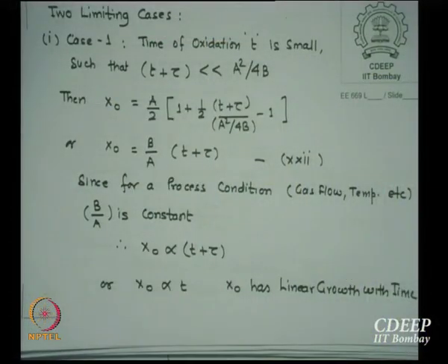So initially what will happen? If t is smaller, what does that mean? Initially oxide will grow linearly with time, and as time increases, we believe it will become parabolic, and let's see how that can happen. Is that clear? So the initial growth of silicon dioxide is linear with time, and then the rate reduces. Can you think why it will reduce the rate? As the time increases, the oxide thickness will increase, so the gradient will decrease. Is that clear to you?